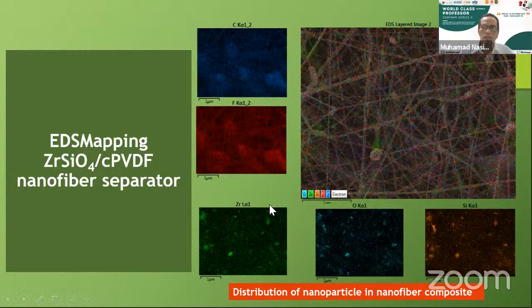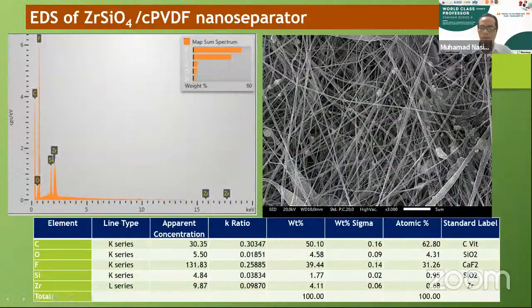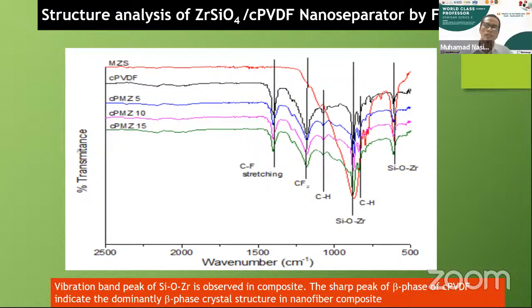We can see here, this is zirconia, this is silica. And this is the composition of the nanofiber composite. And then same, we confirm the structure of the polymer by using infrared spectroscopy. We can see here silica, oxygen, zirconia here. And also we observe the crystal phase of the PVDF in this composite.